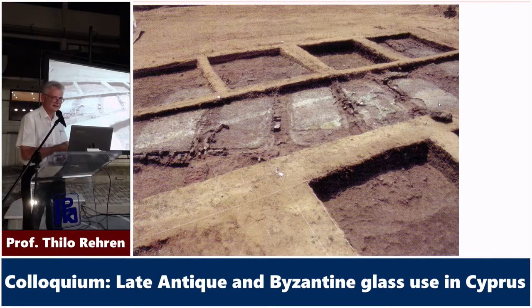1, 2, 3, 4, 5, I think there's a dozen in that row of individual furnaces making glass. Every single one of these furnaces was making around 8 to 10 tons of glass in a single firing. Single firing sounds quick, but it's about a month at least that you need to fire that one furnace to melt your sand with your soda to get a homogeneous block of glass.